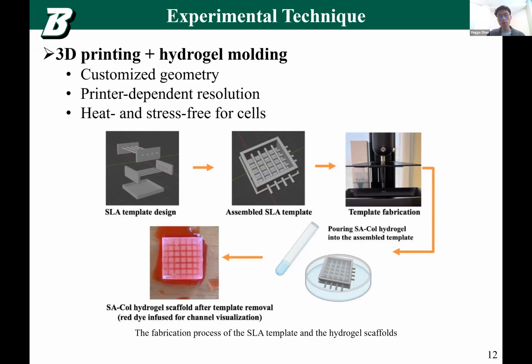And also, we are pouring the hydrogel into this mold. We're not extruding the hydrogel from the bioprinter nozzle, which means the damage to the cells will be minimized. So this is another advantage. We want to have heat and stress-free conditions for cells. And the resolution of the hydrogel is dependent on the printer, no longer on the hydrogel material's limitation.